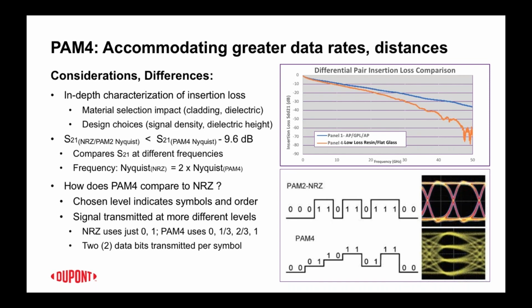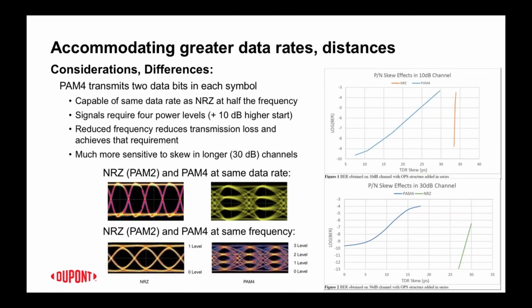So with respect to what's the advantage of the homogeneous material, we're going to move on and take a look at what some of the effects are of skew. So again, one of the considerations for PAM4 is it's a little bit more sensitive to skew. The curves on the right show the skew effects for a 10 dB channel on top and skew effects for a 30 dB channel. Now, again, it's more likely that PAM4 would be used for a longer channel, a 30 dB channel, the complexity of the hardware I'll show in a few slides. But what's important to note here is that PAM4 at either channel length is going to be much more sensitive than standard digital at 2 levels.